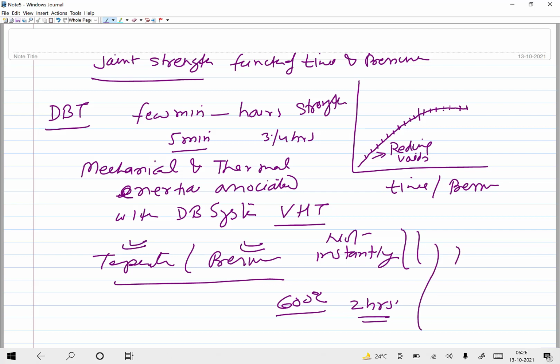So this time required to reach the desired values is simply added, and if we subtract this time, assuming that there is no thermal and mechanical inertia, then we can find that the welding time or diffusion bonding time may be very short. It may be even less than 1 minute to facilitate the diffusion bond, if it can be realized. If the change in pressure and temperature is instant, then it can be very short.